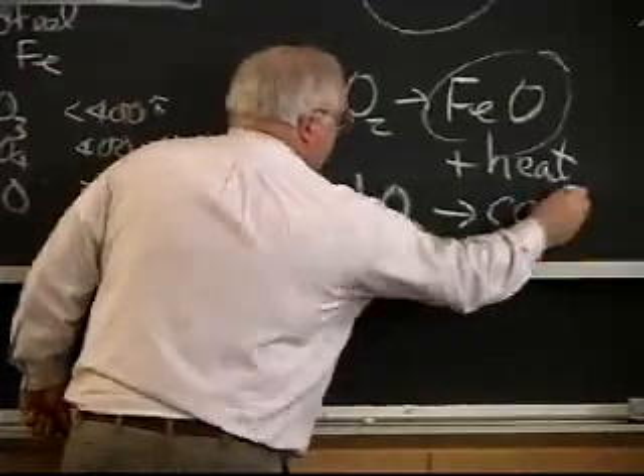Up here, he was looking at the carbon content, and that's what he means by equivalent oxygen purity. If I have Swedish iron or Armco iron, which has almost no carbon, or low carbon steel, and I go down here to razor steel, which is over 1% carbon, here the effective impurity is the carbon in the steel. Carbon plus 1/2 oxygen goes to carbon monoxide, which is a gas. And the carbon monoxide forms a boundary layer because it's not consumed as readily. So down here, it's nitrogen impurity in the air that's dropping my cutting speed. Here, it's carbon monoxide formation because I'm burning the steel. High carbon steels will cut slower than low carbon steels. There is a difference, and it's controlled by the boundary layer. So that's what happens with cutting.